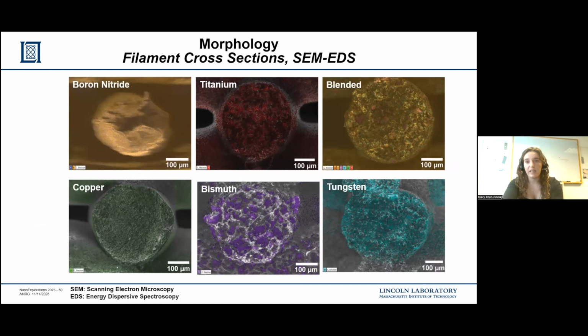So we wanted to see how our nanoparticle fillers actually dispersed within the filaments themselves. As you can see, for pretty much all of our filaments, you get even dispersion of the small nanoparticles throughout. The only exception to this is bismuth, which used larger nanoparticles, and it caused this agglomeration. Additionally, because I'm going to assume I have a microscopy expert or two on here, we are aware that our boron nitride image is not as sharp as the others. The boron nitride filament is a dielectric, so it had a tendency to charge in the SEM. We are currently in the process of retaking this image so it looks just as clean as the others.